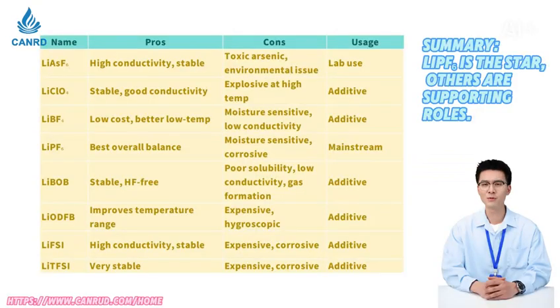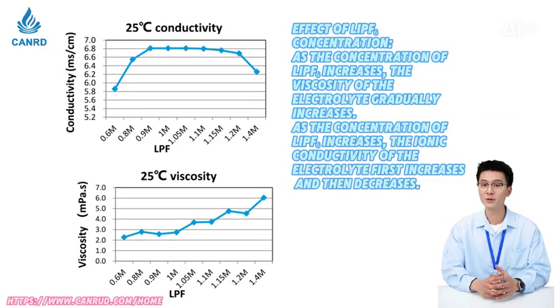Lithium salt is key to the electrolyte. Lithium hexafluorophosphate: balanced and mainstream. Lithium bisfluorosulfonyl imide and lithium bistrifluoromethanesulfonyl imide: stable but costly. Lithium perchlorate and lithium hexafluoroarsenate: risky choices. Lithium hexafluorophosphate is king. Effect of LiPF6 concentration. As the concentration of LiPF6 increases, the viscosity of the electrolyte gradually increases. As the concentration of LiPF6 increases, the ionic conductivity of the electrolyte first increases and then decreases.